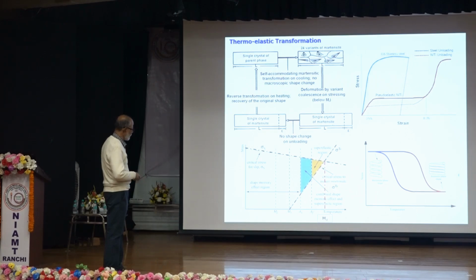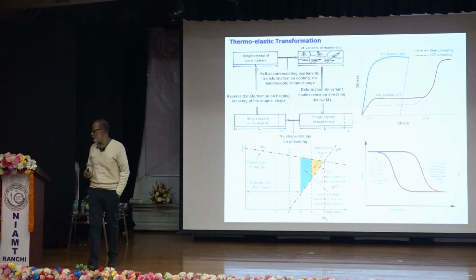So essentially, this occurs below yield strength, because before plastic deformation starts, that's important. No permanent plastic deformation can occur up to this range of strain. And it occurs in these distinct regions. Up to austenite start temperature, it is the shape memory region, as I have said. It occurs in martensite. In the austenitic region, it occurs in austenite. We call it superelastic. So this is basically the background of shape memory effect.